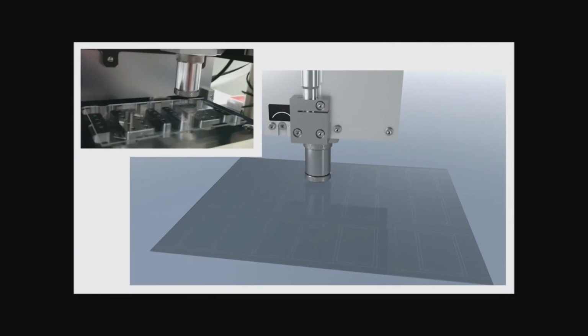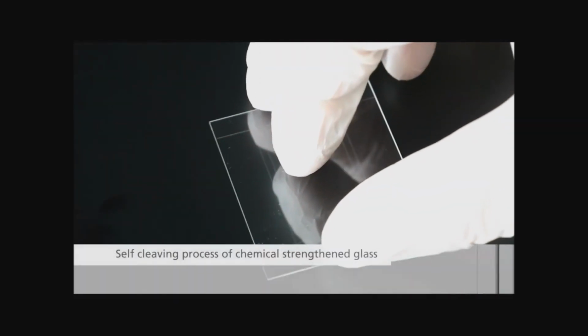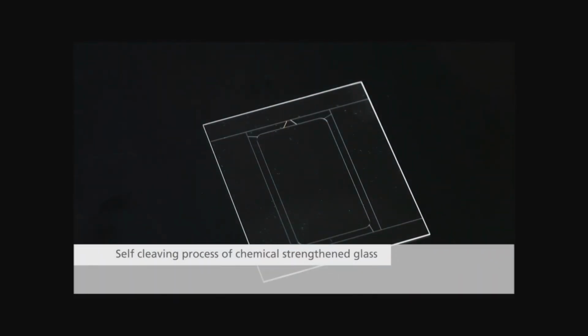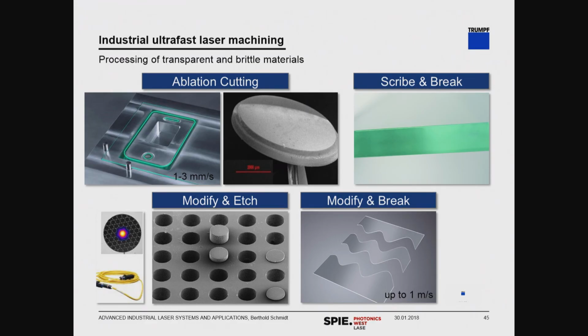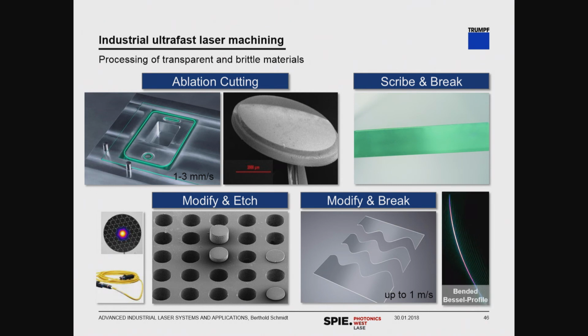It's actually a pretty fast process, and you just have to go through the material once, and then you just put it there, you wait or you blow on it, and due to the chemical stress in the glass, you get your cover glass out without any burrs or additional particles. So it's actually a very nice process. We are naturally playing around with those Bessel beams a lot. For instance, in the future also to create chamfers on the side of the glass, and this is a different DOE we are using for that. And actually all those technologies, I should mention, are also coming already with Kagome fibers as beam delivery for those picosecond lasers.